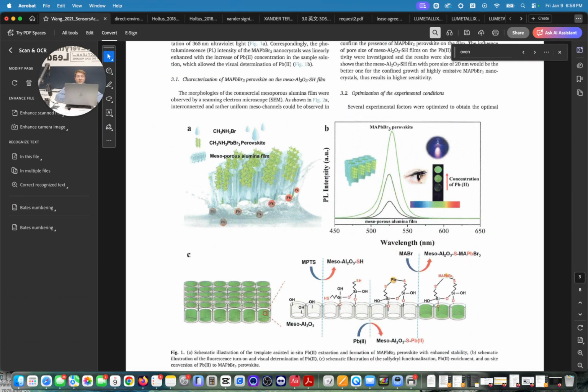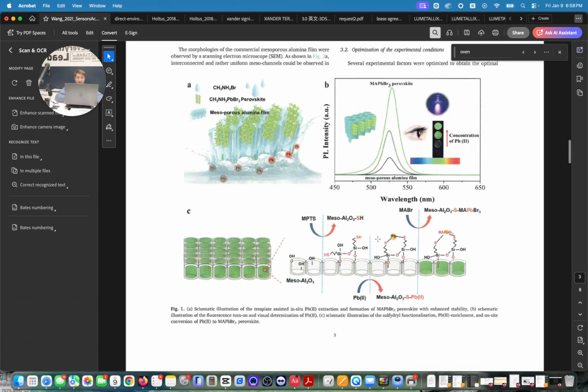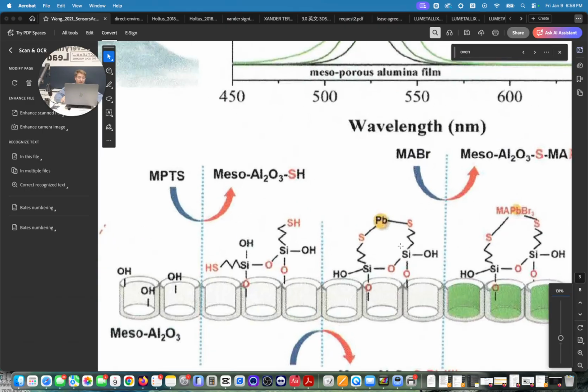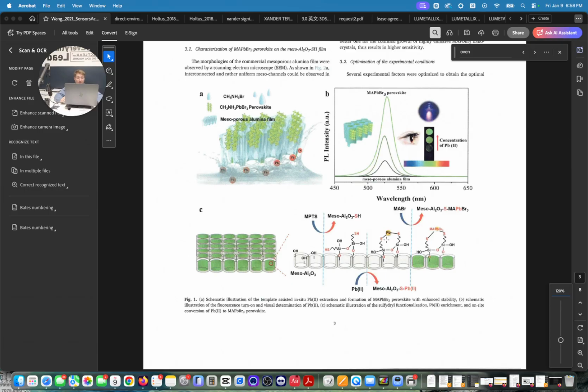So this is a pretty complicated step, but it essentially converts the lead in situ, because the lead is here, right, captured, and then it's converted. So this is the actual operative step that's germane to the patent application and what I'm talking about today. Now the lead was in the water initially, of course, but it was not converted until it was on a solid substrate. And it was chemically bound, as we can see here. It's clearly bound to the sulfhydryl moiety, and that's not a weak bond at all.